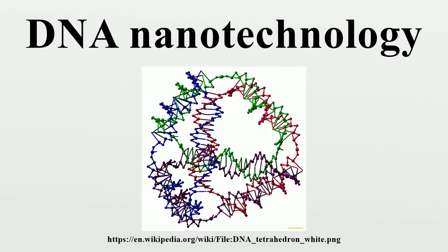These cascades are made energetically favorable through the formation of new base pairs, and the entropy gain from disassembly reactions. Strand displacement cascades allow for isothermal operation of the assembly or computational process, as opposed to traditional nucleic acid assemblies' requirement for a thermal annealing step, where the temperature is raised and then slowly lowered to ensure proper formation of the desired structure. They can also support catalytic functionality of the initiator species, where less than one equivalent of the initiator can cause the reaction to go to completion. Strand displacement complexes can be used to make molecular logic gates capable of complex computation.